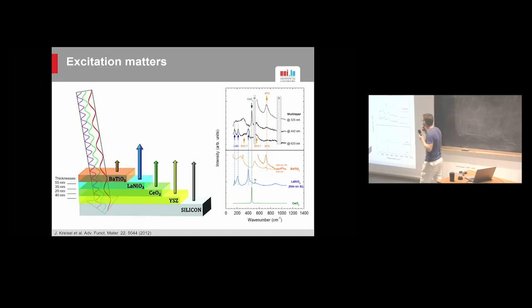So let's get to it. So below here, those are reference spectra that have been measured on pure powders, pure compounds. And those are the spectra that you can measure on this sort of multi-layer. And you see that they are really different. So if I take the first one, this is excitation at 325, so this is in the UV. I think it's 3.8 eV or something like that, but anyway, it's above the band gap of barium titanate. So you're coming with your UV laser and you're hitting barium titanate above the band gap. So it basically absorbs everything, so you're blind to everything that's below. So what you see here is essentially one peak that corresponds to your barium titanate, and you don't see the rest. Quite cool.